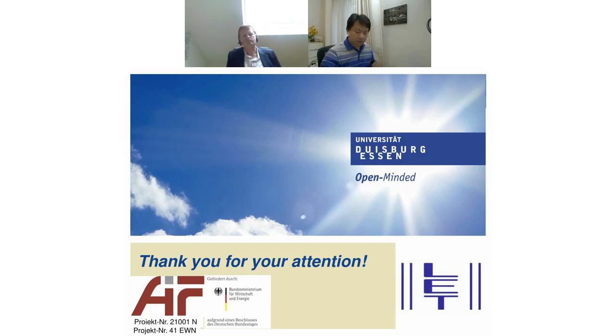So maybe we will change the electrolyte a little bit in this project also. I see. Okay. And I also have one question regarding zinc polyiodide. Zinc polyiodide is very interesting. Of course, we test that in our lab, but not slurry type. We use the hybrid flow where zinc is deposited on the carbon felt or nickel foam, something like that. We think that the big problem is the crossover of iodine.